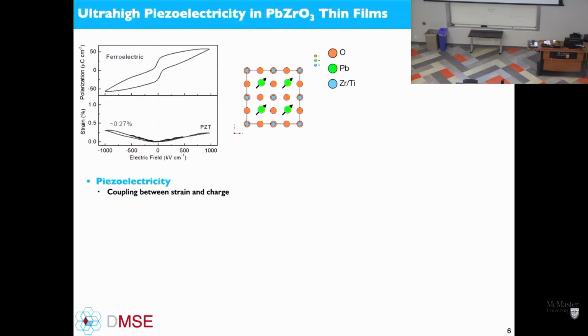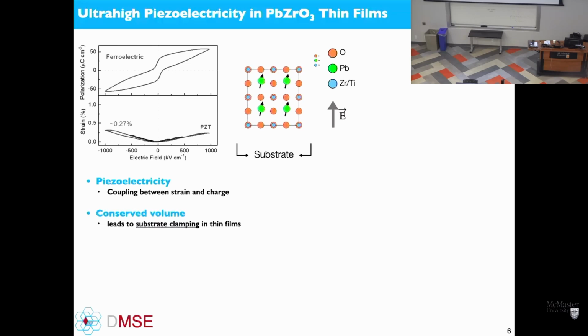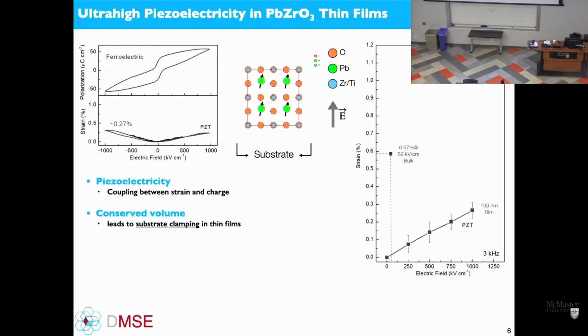Now, coming back here for a moment, if we look at a ferroelectric like PTO, or a PZT, for example, your dipoles are going to rotate with the field, and you get some strain out of that due to the piezoelectric response. Now, the problem is that if you grow the sample on a substrate, the substrate is going to want to clamp that unit cell and basically lock in the structure so that polarization becomes less easy to rotate. And as a consequence, if you grow the bulk material, PZT, you can see it has a fairly large strain with relatively small electric field.